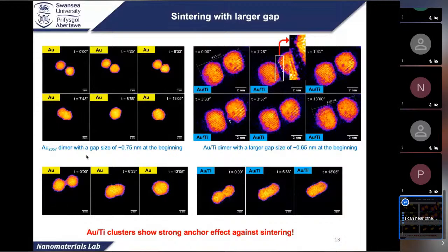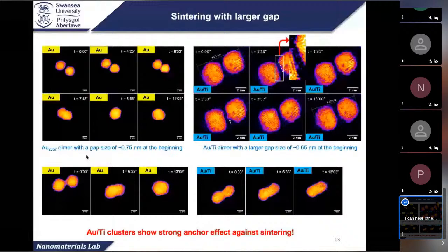Regarding the CO oxidation activity, this is the very first test. We found that the gold titanium is active for the CO oxidation, but gold shows no activity because it's on the silicon dioxide support. There's a support effect as well. But this is the very first result, so I didn't put it here. This is still ongoing.